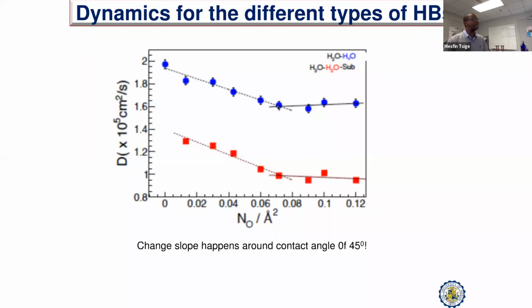But surprisingly, there seems to be a saturation in terms of the diffusion coefficient at around 0.07. When we map this back to the contact angle, it seems to be at around 45 degrees. So at a contact angle of 45 degrees, we see that the dependence pretty much changes and doesn't show any dependence thereafter. So we found this 45 degrees to be very intriguing. I will explain to you in the next slide.